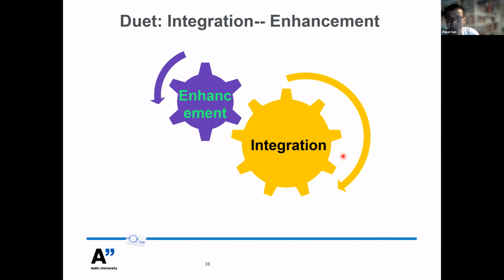As we discussed at the beginning, we would like to integrate the current 2D materials with different silicon devices or fiber devices for different applications. On the other hand, I would like to highlight that although the nonlinear response of the 2D materials is very, very high, if you think about the thickness, it's very, very thin. However, the absolute value of the conversion efficiency inside of the monolayer 2D materials is very, very weak.